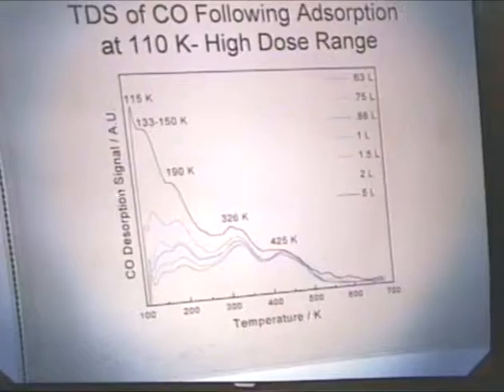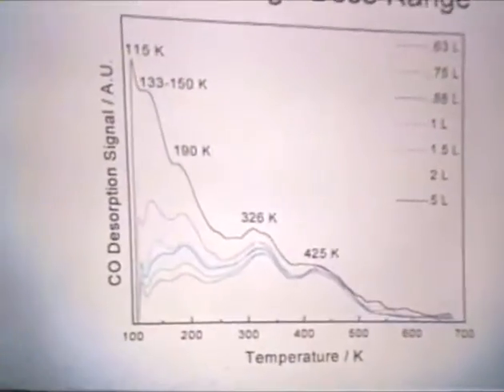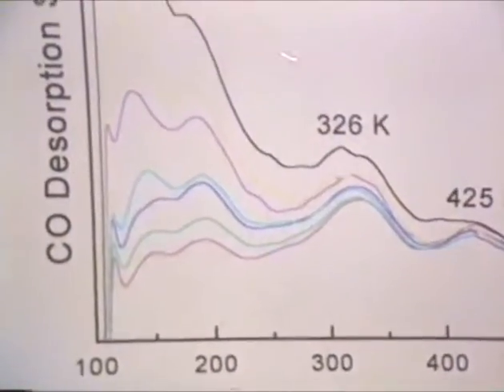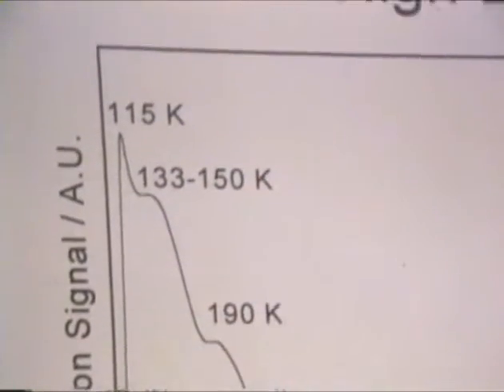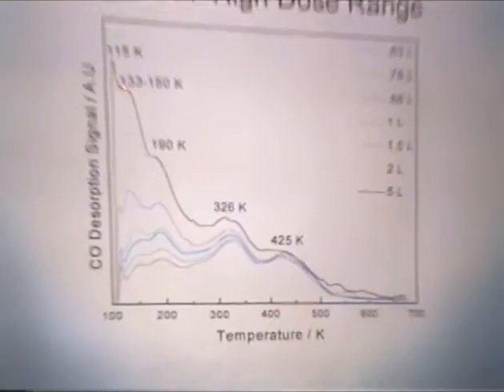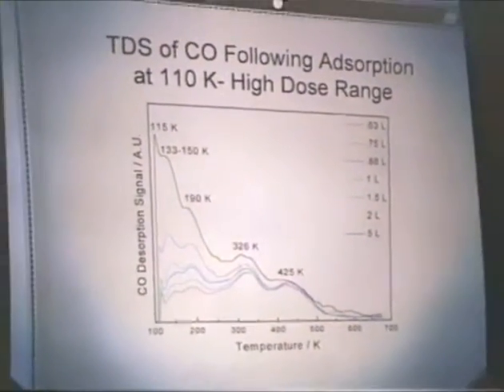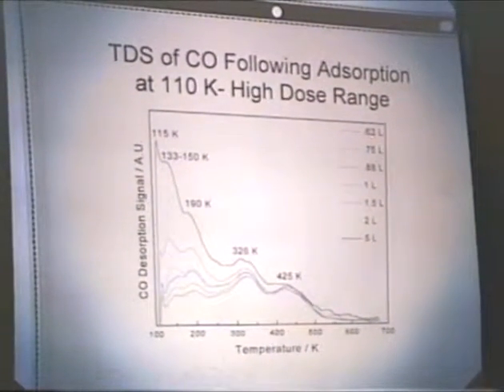As we move to the high dose range, again at 110 Kelvin, you see that the lower temperature states begin to become the most highly populated, and the high temperature states now are at a constant peak temperature and do not shift with increasing coverage. And one of the lower temperature states goes from 150 Kelvin at 0.88 Langmuir down to 133 Kelvin at 5 Langmuirs.